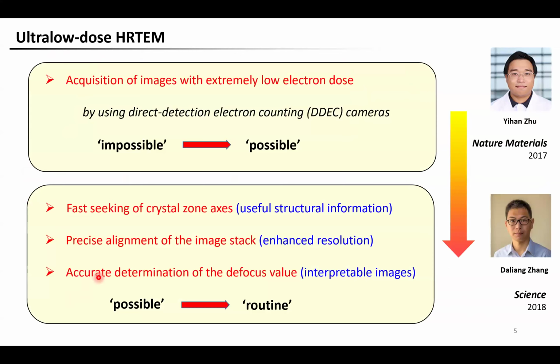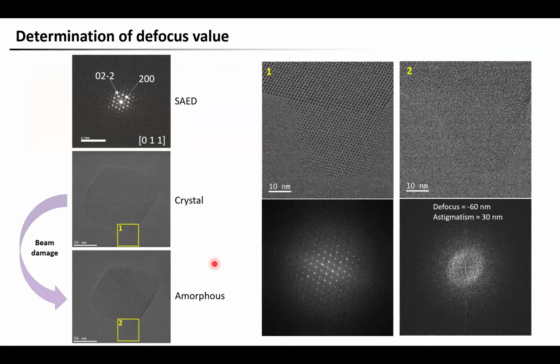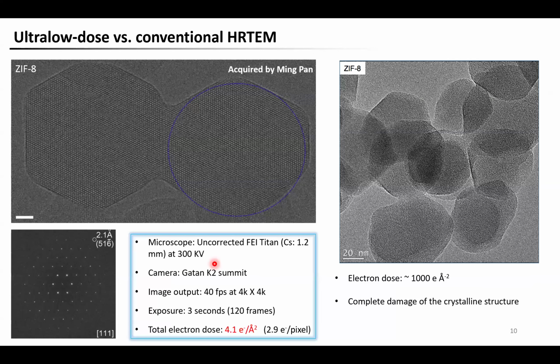So using this amplitude filter, we can achieve single frame-based alignment of the image stack, so we can get better resolution. And the last problem is how to determine the defocus value of the image. Because for a TEM image to be interpretable, we need to know the defocus, right? In HRTEM, the common practice is to take a focus series. But now we are dealing with highly sensitive materials. So even by using the new camera, we can obtain at most only one image before the structure gets damaged. So with only one image, how to determine its absolute defocus value? We propose a new strategy to achieve this. Okay, so today I will skip these technical details of these methods, and if you are interested, you can refer to our publication.